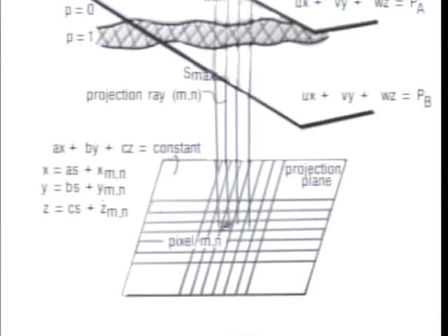Now, how can we determine what we are seeing? We can, on the computer, model the transmission electron microscope experiment by passing rays or tracing rays through a simulated substance whose interface is a numerically calculated surface that we guess is going to be the surface we see in reality, in the actual experiment.